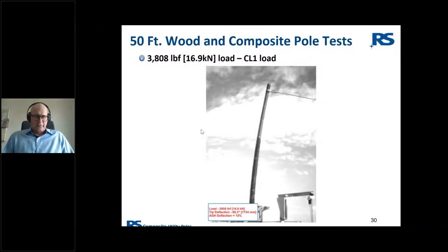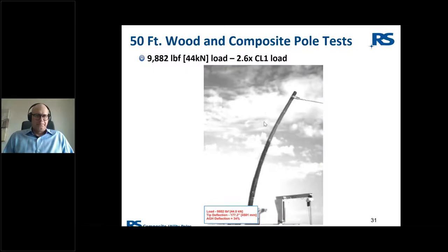And here we have, at actual factored class one load per CSA grade two construction, the tip deflection is 68.3 inches, which is 13%. So right about on trend again with the mean value of the ANSI O5.1 predicted values. And what we see here, typically, is that the published values of the RS composite pole performances are higher than the actual performance. So you're seeing a little bit more conservative deflection performance here than what was published in the tables, which is typical throughout the range. Okay, we'll go to the next slide.